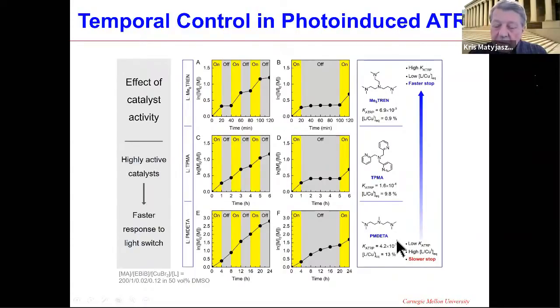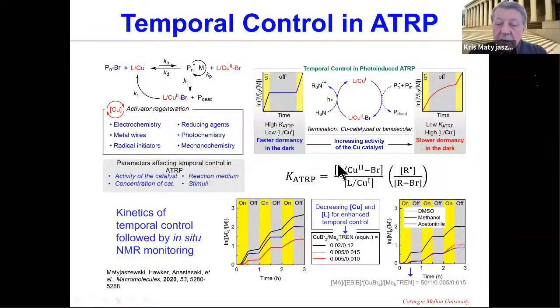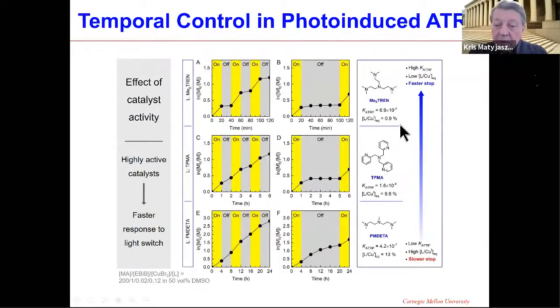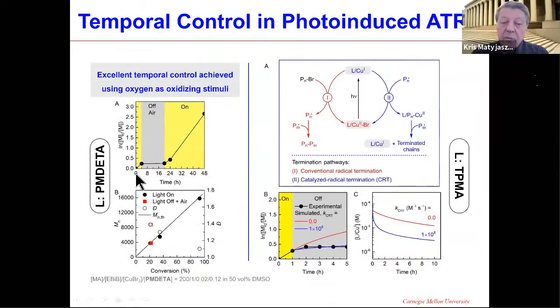Because you have a 100 times lower equilibrium constant, in that case, the ratio of copper-1 to copper-2 species is dramatically different. So in a case of this PMDETA, you could see that here you have 13% of copper-1 left, and in a case of hexamethylated TREN, only 1% of copper-1. So it's enough to kill this 1% of the activators, and the reaction would stop. In a case of PMDETA, it can continue unless you reduce copper-1 or oxidize copper-1 to copper-2. So this is really what happens if you expose it to air.